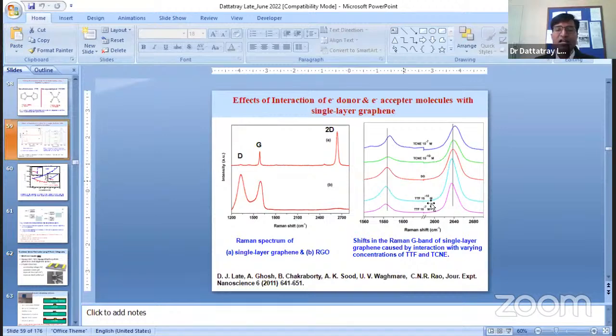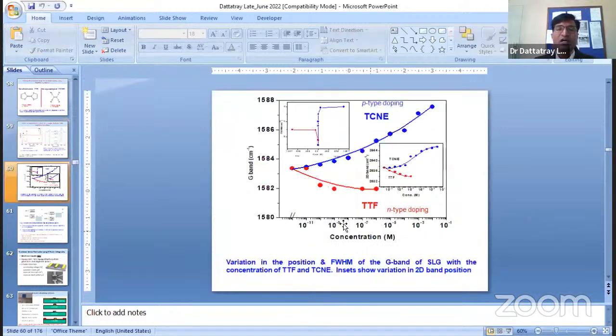And what we find, very surprisingly, is that with increasing concentration of TCNE or TTF, there is a shift in the G band position. You can see with addition of TCNE, the G band shifts towards the higher frequency side, and with TTF, it goes to the lower side. So this completely indicates that when you add TCNE, graphene becomes more P-type, and with addition of TTF, graphene becomes more N-type.